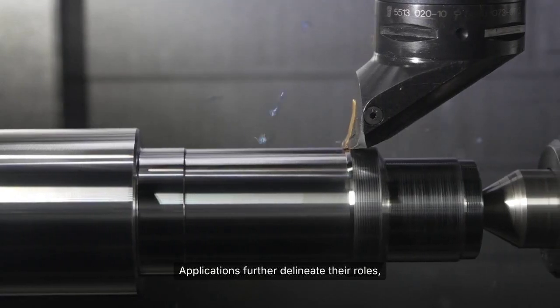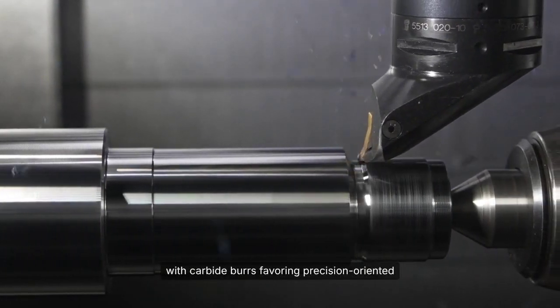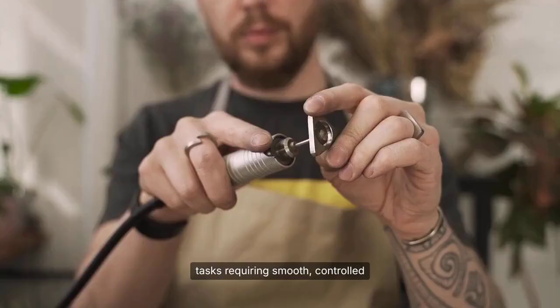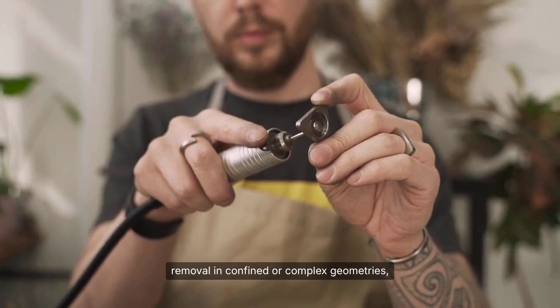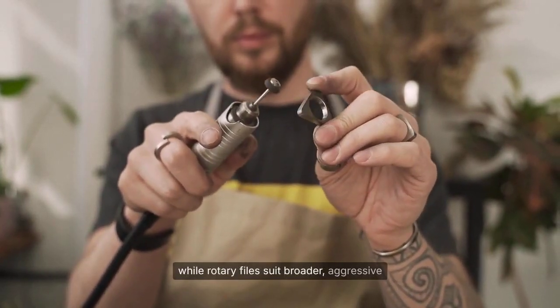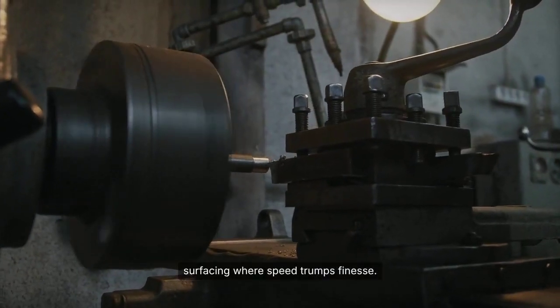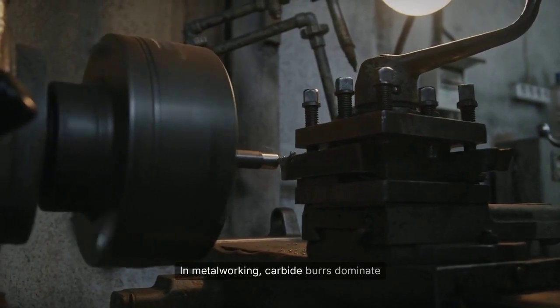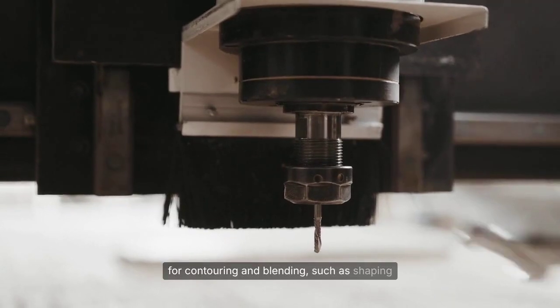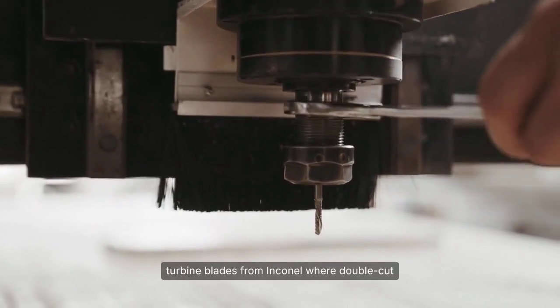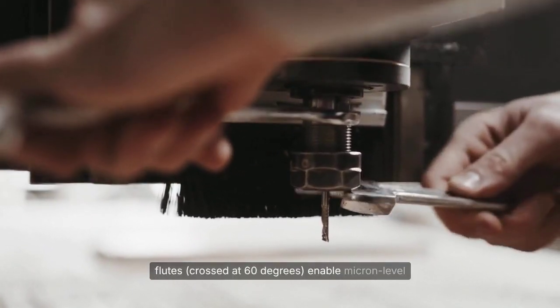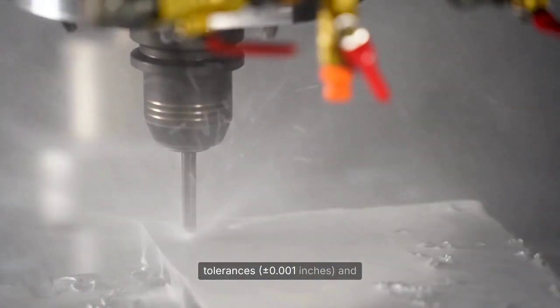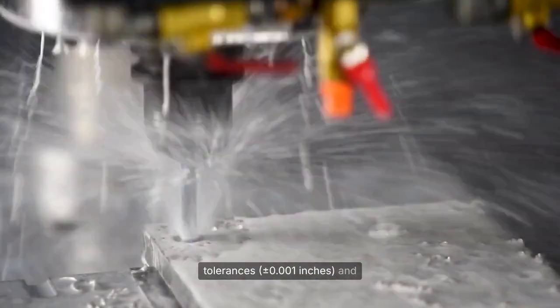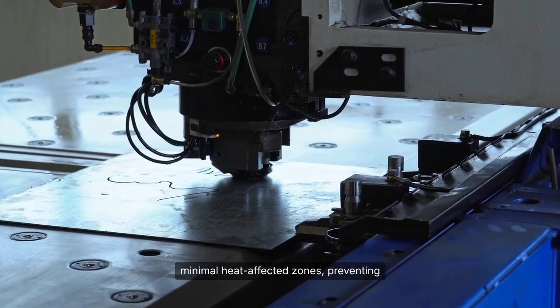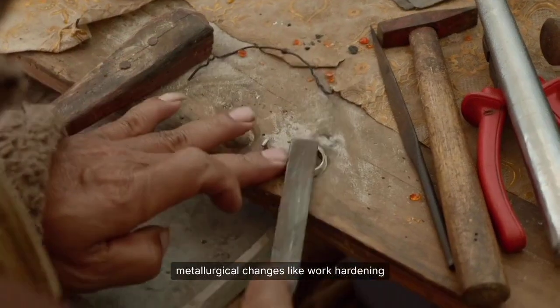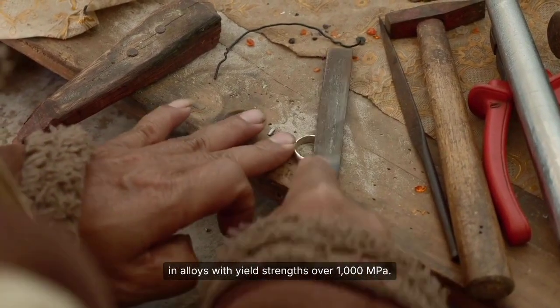Applications further delineate their roles, with carbide burrs favoring precision-oriented tasks, requiring smooth, controlled removal in confined or complex geometries, while rotary files suit broader, aggressive surfacing where speed trumps finesse. In metalworking, carbide burrs dominate for contouring and blending, such as shaping turbine blades from Inconel, where double-cut flutes, crossed at 60 degrees, enable micron-level tolerances, plus or minus 0.001 inches, and minimal heat-affected zones, preventing metallurgical changes like work hardening in alloys with yield strengths over 1,000 megapascals.